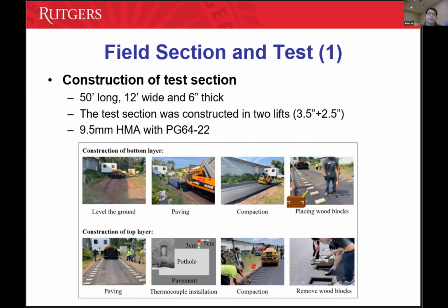And then, in order to make the project more practical and easier for testing, we used a test section instead of going out to real pavements, because in that case we cannot get cores back, and also the irregular shape of potholes makes testing difficult. So we built a small test section at the campus. We had a 6-inch asphalt with 2 lifts, 3.5 plus 2.5. We assumed the pothole depth is 2.5 or 2 inches. Then we made an artificial pothole by putting in some wood blocks after paving and after initial compaction, and then took out the wood blocks. The purpose is to be able to take cores around the edges so we can do all kinds of testing.